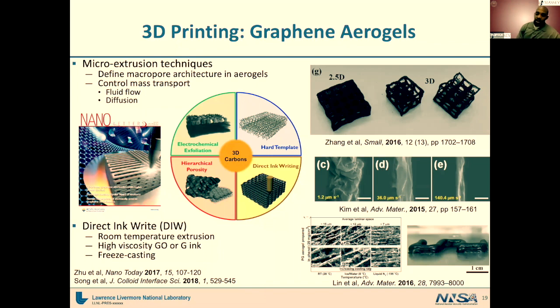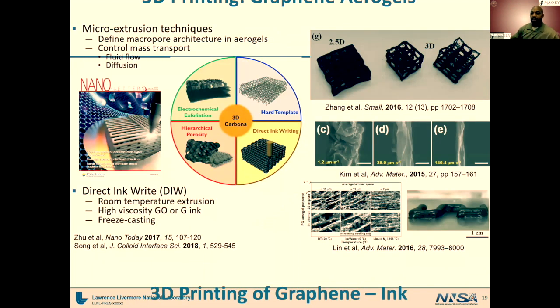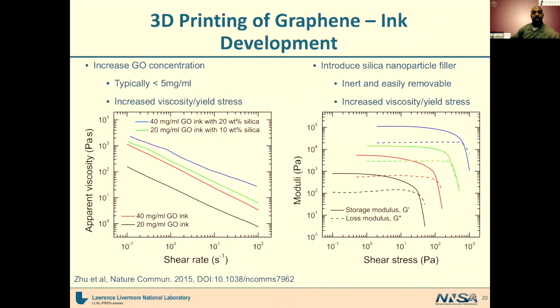So you need to have a fairly viscous ink, not too viscous such that it can't flow through a nozzle, but you want it to be viscous enough so that it's really something like toothpaste. When you push toothpaste through the tube, it flows out like a liquid, but then once it hits your toothbrush, it very quickly goes back to being a solid and doesn't run off of the toothbrush. That's the exact sort of rheology, called thixotropic behavior, that we're looking for in our inks.